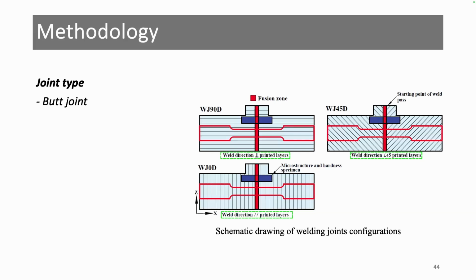For example, here we defined that this joint is WJ90. It means that the welding direction was perpendicular to the printing, whereas here, WJ0 means that the welding direction was parallel to the printed layers, and here we have WJ45 due to the angle of 45 degrees between the welding line and the printing direction.